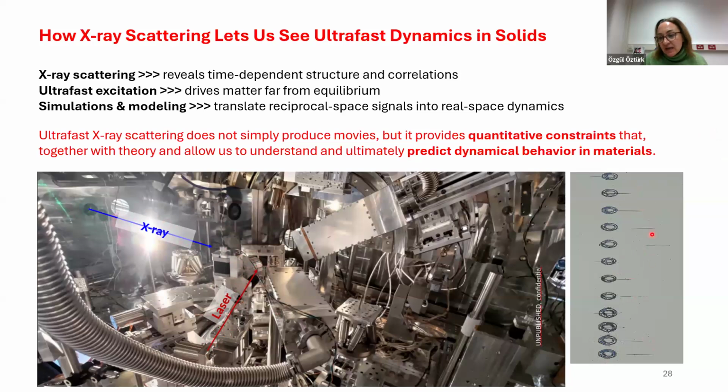And here you see an optical microscope image of the real samples. These circles are because of the laser impulse, so they are burned. And these lines are the X-ray probing. So this means the first one is fine. There's an overlap. We can use this, for example. This one is perfect. This one is, yeah, not so good.